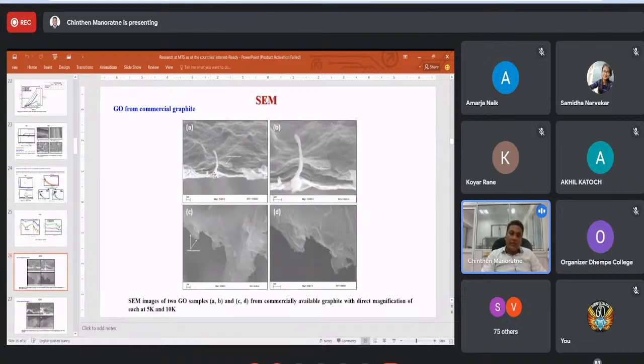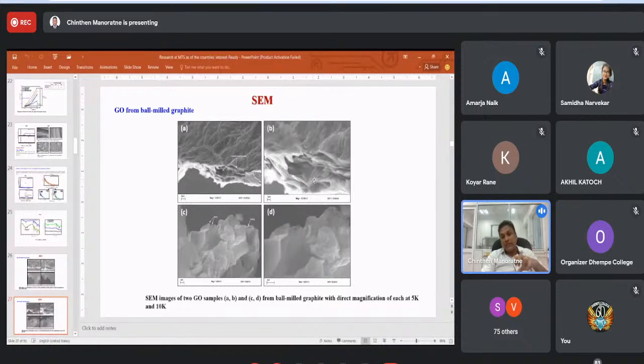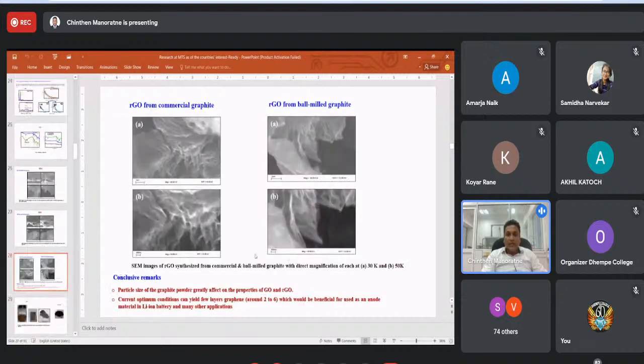Now, you can see these SEM images I took of the graphite oxide produced from commercial graphite. You can see the interlayers are split very nicely. And this shows the reduced particle size graphite powder. You can see the internal layers also split further. That means the reaction has taken place in a very efficient way. Now these are the corresponding higher magnification images, and this is reduced graphite oxide or graphene from two sources. You can see very thin, transparent-like layers synthesized from ball mill graphite.